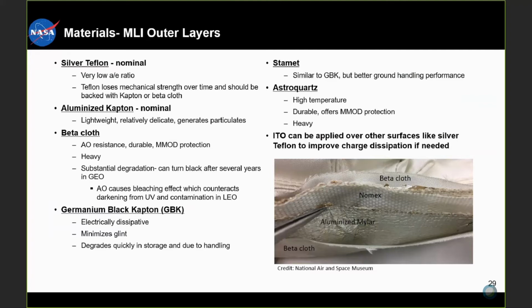The next material is beta cloth. It offers atomic oxygen resistance, it's durable, and it offers MMOD protection, although it is heavy and it does see substantial degradation. This material can end up turning black over several years in GEO. Although atomic oxygen does cause a bleaching effect, which will counteract the darkening from the UV and contamination. But again, this is in LEO.